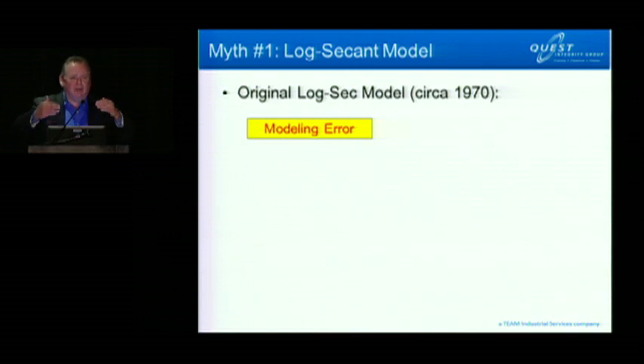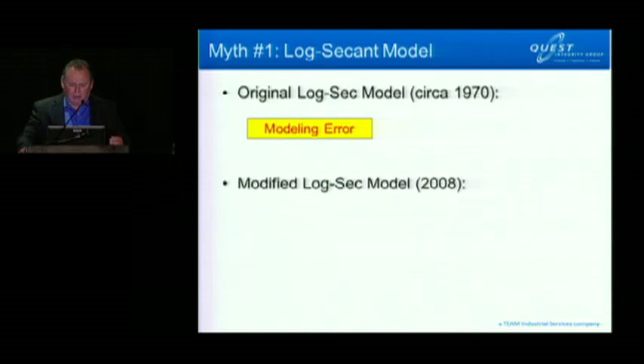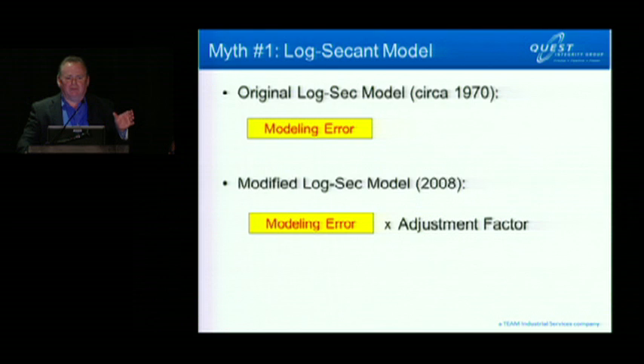because that's what science and engineering is about. We try something, we develop a model, and for its time it was a pretty good model, but then some shortcomings came out of it. For one thing, it produces some unusual results for very shallow cracks. As a crack gets shallower and shallower, it starts predicting burst pressure results that make no physical sense. So then came the modified log secant model in 2008, and rather than fix the modeling error, it left the same modeling error in there, but then applied an adjustment factor to get rid of